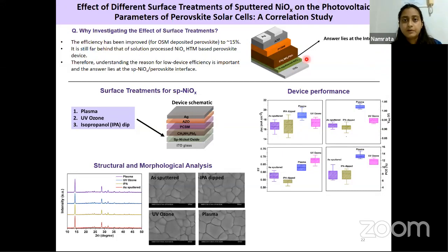So here we have taken three different surface treatments and compared them with the as-sputtered nickel oxide substrate. The three conditions are using the oxygen plasma on sputtered nickel oxide, using the UV ozone, and using isopropanol as a liquid for treating the surface of sputtered nickel oxide. And why we chose these three treatments as compared to many other treatments reported by different papers is that these are easier to do, and these are faster, and these do not involve any chemicals like potassium chloride or NaCl.